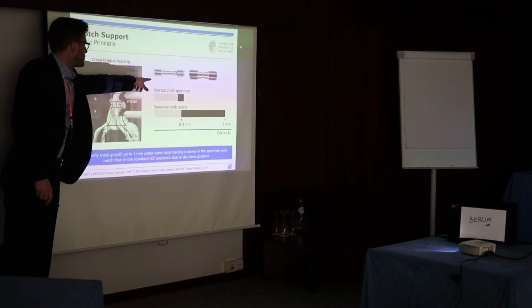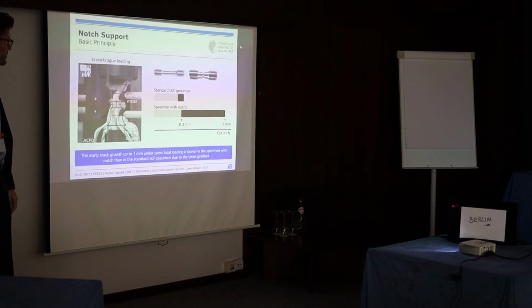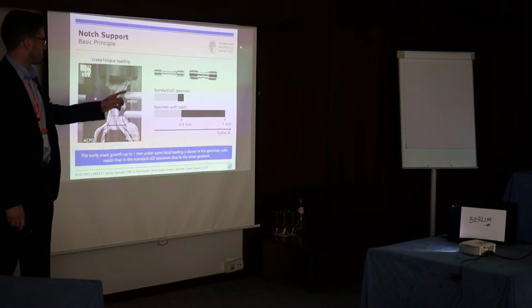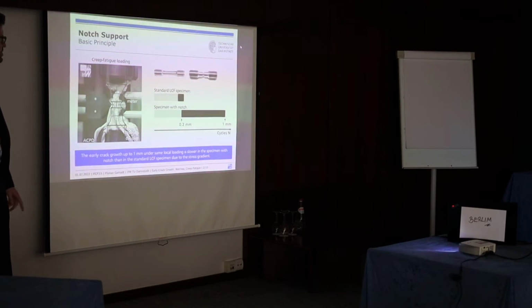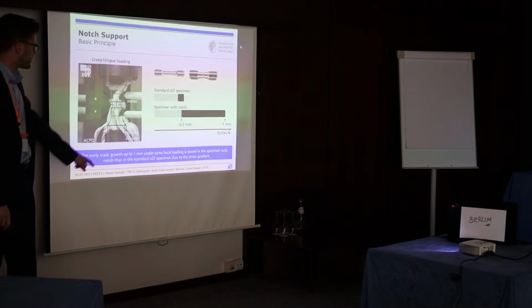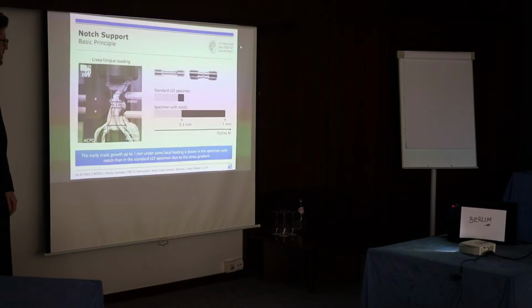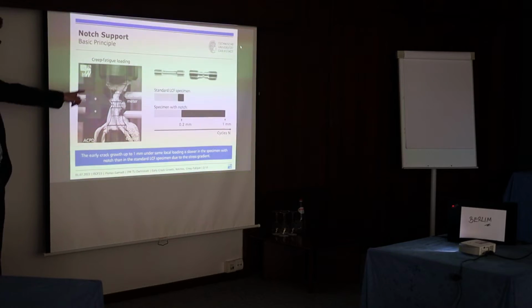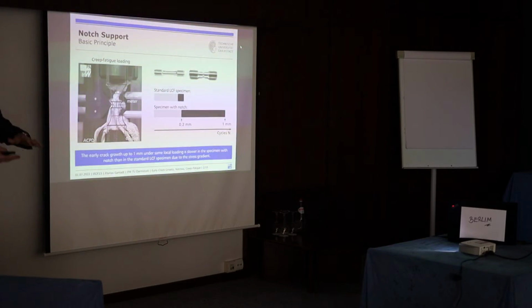The standard is to use a uniaxial standard LCF specimen, and we then use a round bar specimen with a circumferential notch to determine this effect. And you can see by these schematic bars here that the cycle number is much higher for the specimen with the notch. We do the tests in our high temperature lab in Darmstadt. You can see one of our test rigs where we load these specimens with a cyclic mechanical loading and a high temperature. In this case, I'm talking about heat-resistant steels, so we have temperatures of 600 degrees Celsius here.